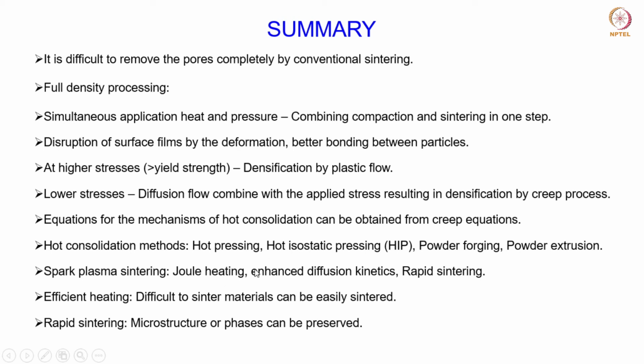And we have covered these processes with regard to full density processing: hot pressing, which is basically uniaxial pressing in a die with the simultaneous application of heat and pressure. We also talked about hot isostatic pressing, in which the pressure can be applied from all directions uniformly, unlike the die pressing in which the pressure is applied along a particular direction, which is basically along the axis of the die. So this leads to a better densification when the pressure is applied uniformly through all directions.